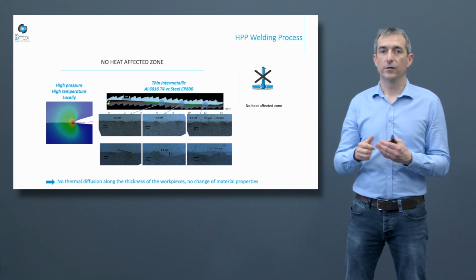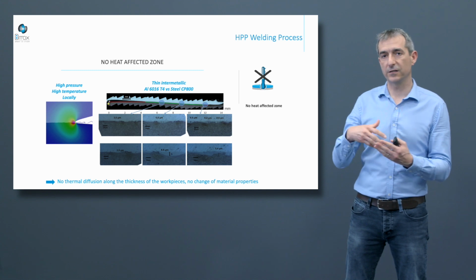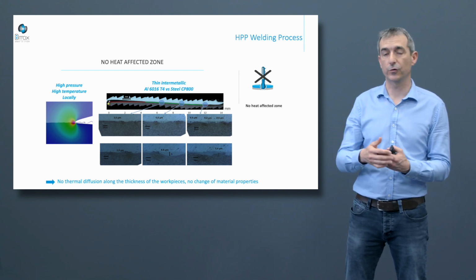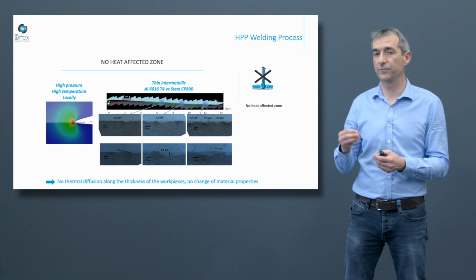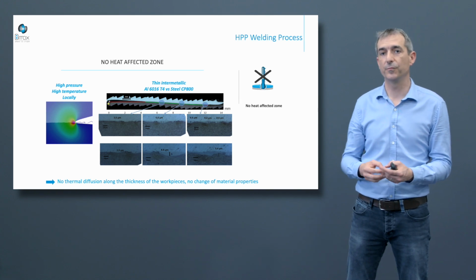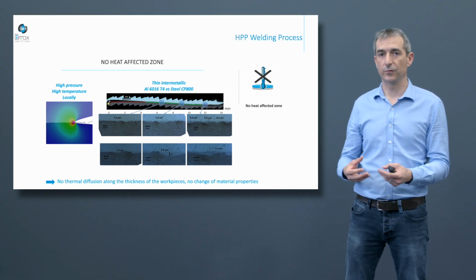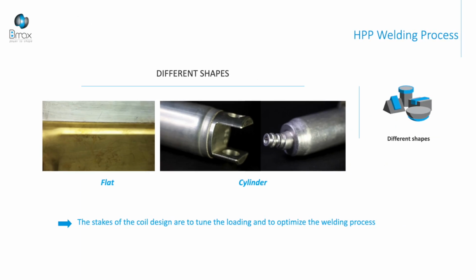By this way, we have no thermal transfer, no thermal diffusion in the component. So the temperature at the end is very low, and we don't change the mechanical properties of the materials. That's why we have no heat-affected zone. To conclude, the last advantage of the MPW process is that we can address different shapes. We are able to weld flat geometries, cylinder geometries and complex shapes. The stakes of the coil design is to tune the loading and to optimize the welding process.